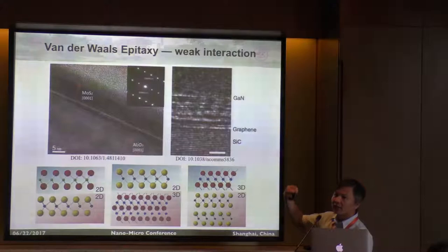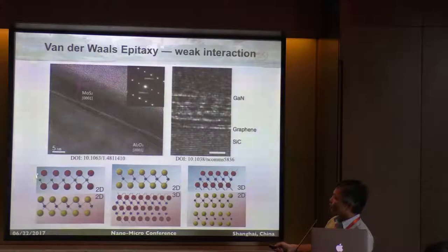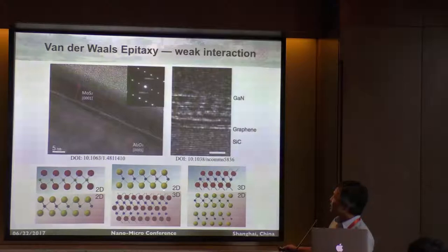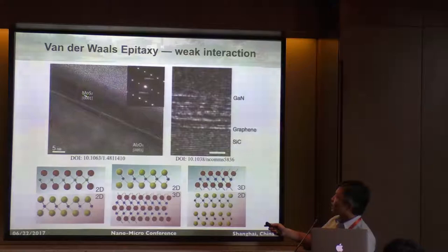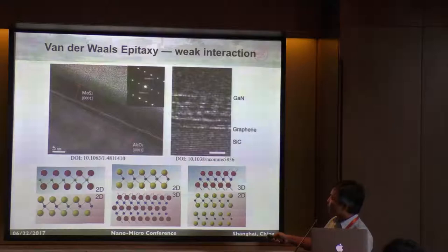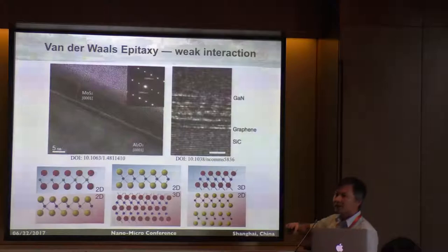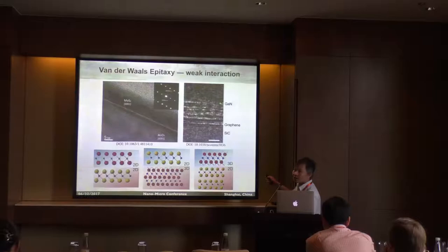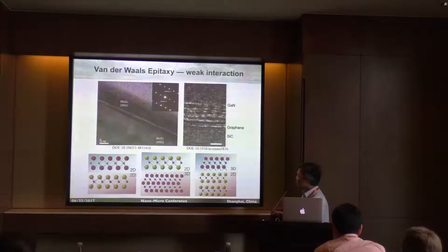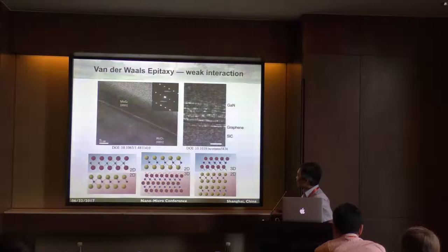Because muscovite is a two-dimensional layer material, when you put something on top you can have epitaxy. We call this van der Waals epitaxy. The key is that you have very weak interaction between your substrate and your materials. One type is growing 2D layer materials on 2D layer materials. A second type is building 2D layer materials on top of 3D substrates — for example, using a sapphire substrate and growing MoS2 on top. You can also do the opposite: have 2D layer materials as your substrate and put 3D materials on top — for example, graphene with GaN nitride deposited on top — and then peel from these layers to get a flexible device.